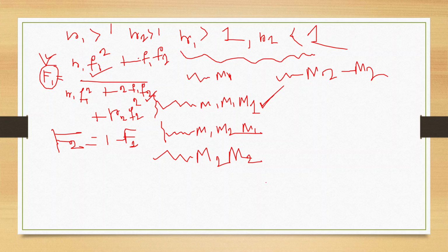So they continuously keep pouring monomer 1 or M1 from outside, so that there is a constant concentration of M1 in that particular reaction mixture, okay? So they are continuously putting M1 in the reaction mixture, so at no point do you get a concentration deviation. As soon as M1 is being consumed, you are also supplying it from the outside, so the overall composition remains the same. They try to do it that way, okay.